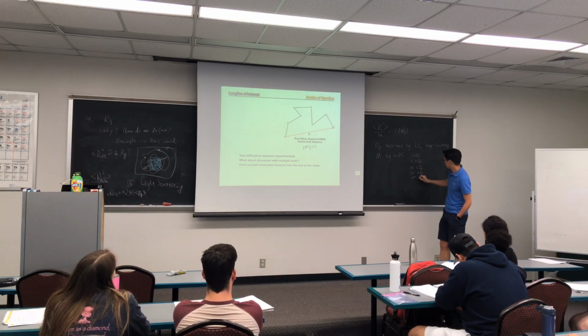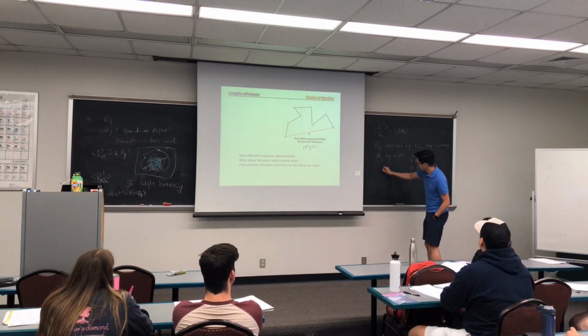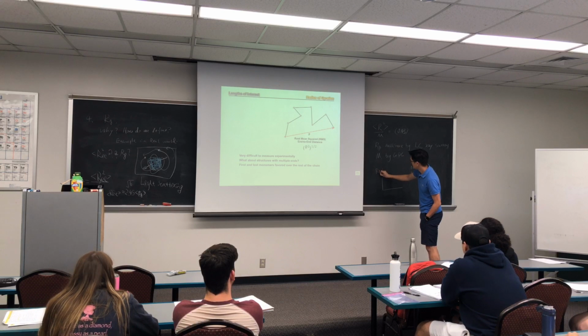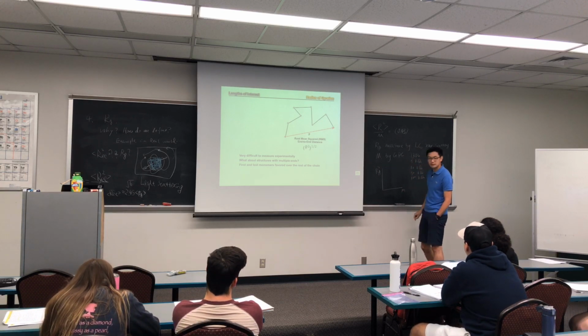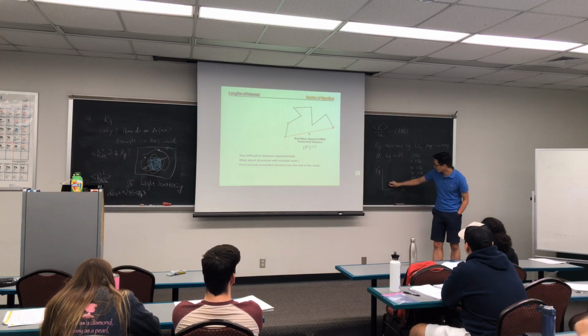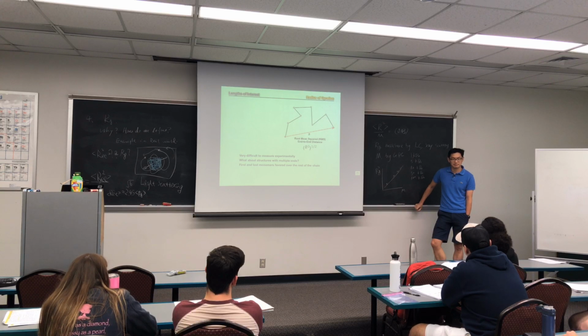Then you can measure the RG and get the plot of RG squared versus molecular weight. In this case, you can generate a few data points, and this will tell you how they are linked. That's typically how people use RG, how they measure it, and how they apply it to their polymers. Any questions so far?